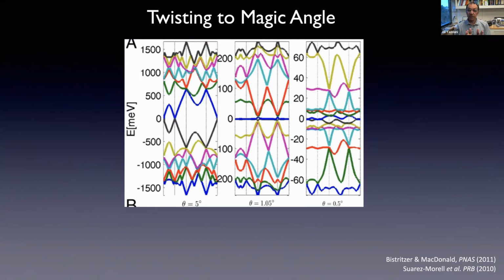So as you see in the middle of this panel, first of all, I note that there are a lot of bands here on either side. And remember that this is an extremely complicated material. It's very chemically simple in the sense that it's just 2 layers of graphene. But if you ask what the unit cell of this material is, because it's quasi-periodic, it will have a unit cell that can involve maybe 10,000 atoms. So it's very difficult to do a very realistic calculation of the electronic structure of this material because of the large number of atoms within the unit cell.